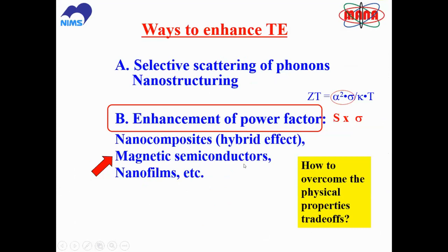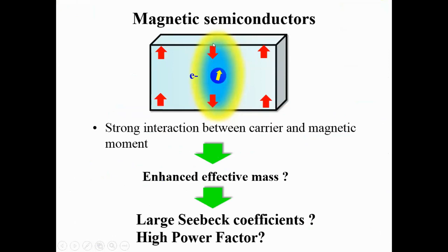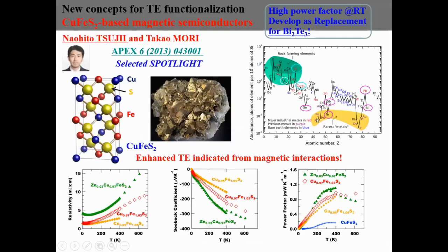And now the main part. This was originated by us, mainly by my colleague Tsuji-san, who initiated this work on the magnetic semiconductor. It came a little later after first finding a good example, but of course the background is that a magnetic semiconductor can have a very strong interaction between the carrier and the magnetic moment. So this can lead to a heavier effective mass for the electrical carrier, which leads to a large Seebeck coefficient. Of course, it can lead to lower mobility, but the Seebeck coefficient is most important. It's squared in the power factor. So with this, we thought we could enhance the power factor, the combination of the Seebeck and electrical conductivity.